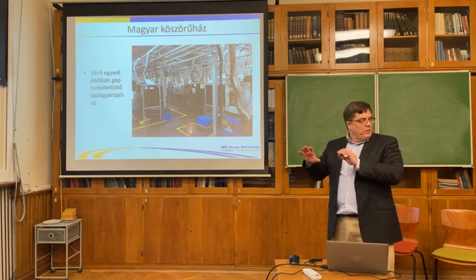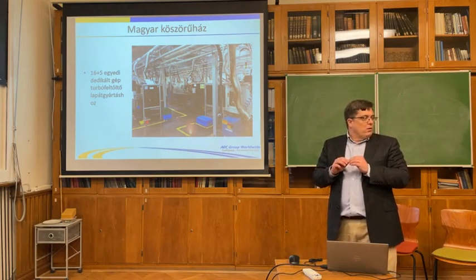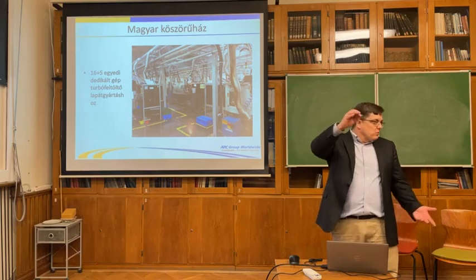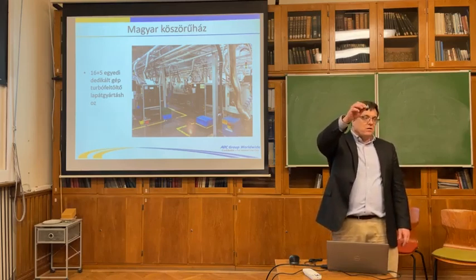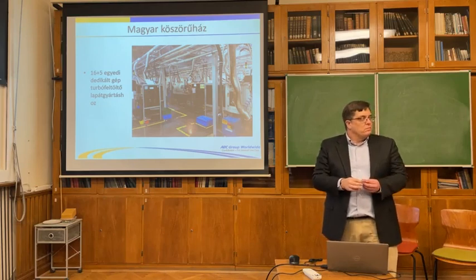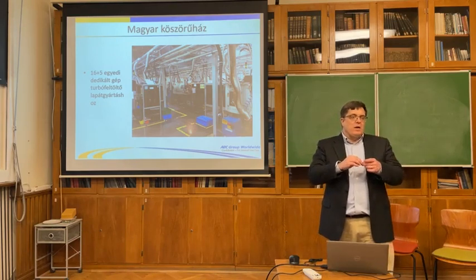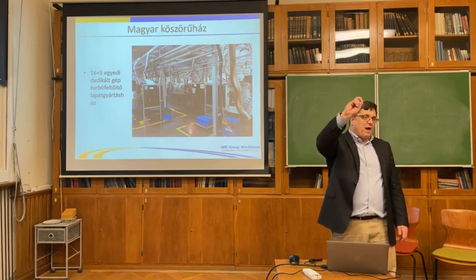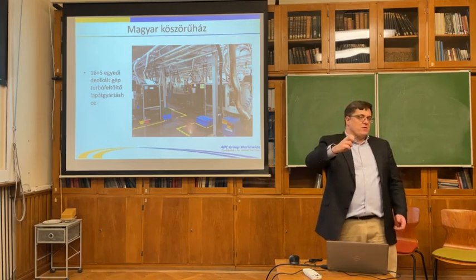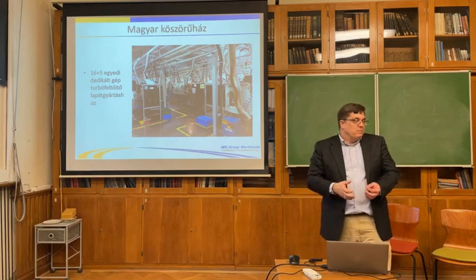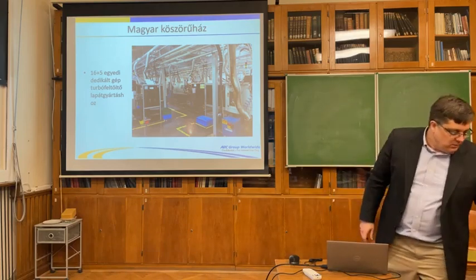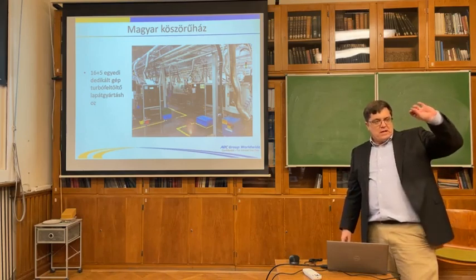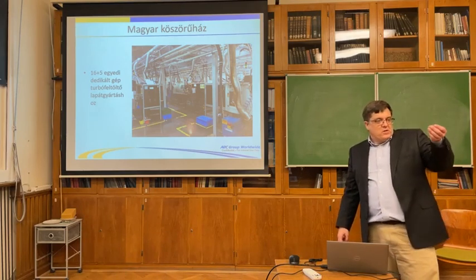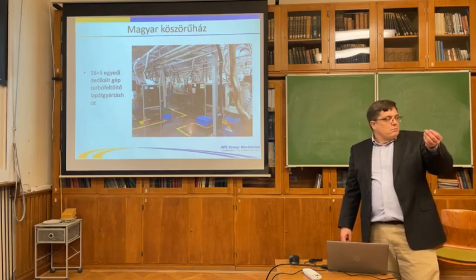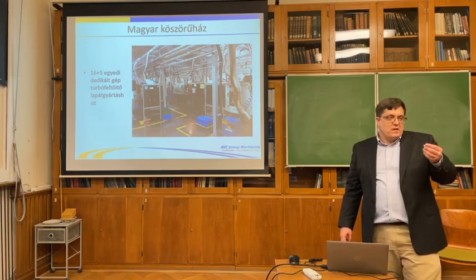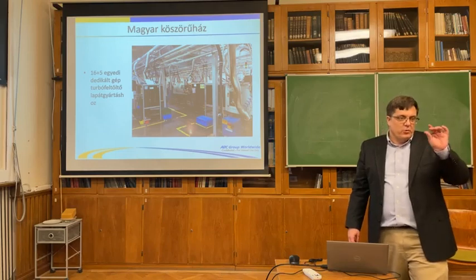And we have 16 of the old type, and we now have 5 of new, more efficient machines. We're pushing through 8 to 10 million of these a year with this grind. So it's really important. But we don't get that in MIM. This is an example where you have to have this grinding to have these really tight dimensions at this really high volume. But that's when it goes into the automotive world. And this is 310 stainless steel called HK30. It's relatively soft actually, but it withstands high temperatures. And that's what it's designed for, the inlet section of our turbocharger.